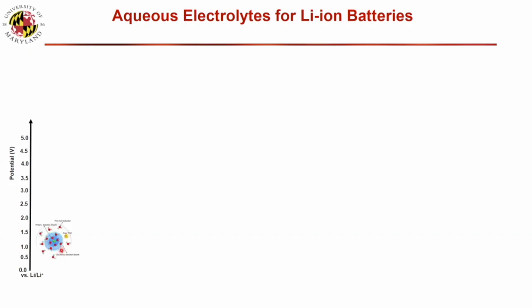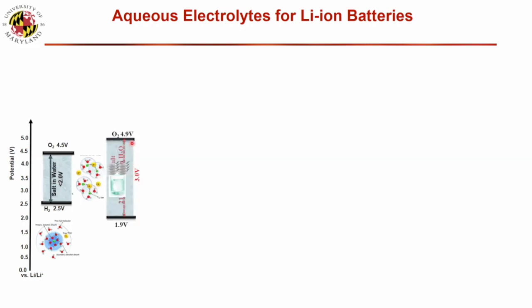In aqueous, the solvent is the same as in organic: the lithium is solvated with water, so they limit the window. If we put in a lot of salt, it is the same as in organic. We really can extend the window because the salt has the opportunity to reduce and then form SEI. Another unique point is if we put a lot of salt in the water and they are separated with some high-order polysulfide or some really hydrophilic salt solution, that brings us new opportunity for a new type of battery.